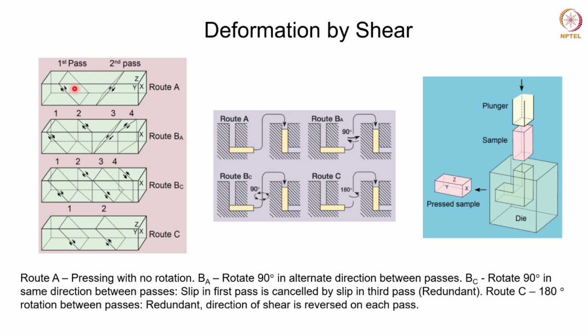So in route A, as I said, there is no rotation at all. You can see how a particular element inside this billet will be deformed as the number of passes increases. And then here in route B, it is rotation in alternate direction between passes. This is the first pass, and then it is rotated 90 degrees in the next pass, and again 90 degrees in the opposite direction, and so on. And BC is 90 degree rotation in the same direction, as you could see. This is the first pass, then 90 degree rotation in the second, then the third also again 90 degree rotation in the same manner, and so on and so forth. And in case of route C, you can see it is rotated 180 degrees.